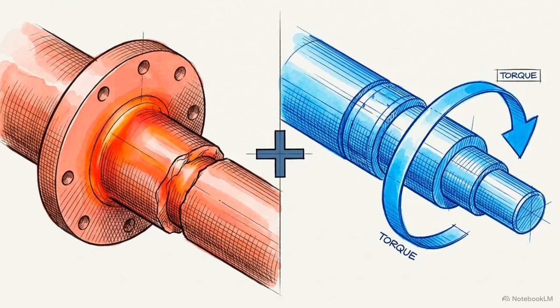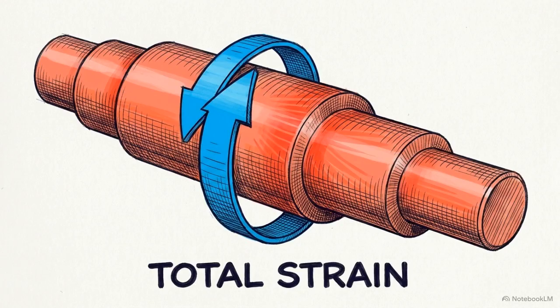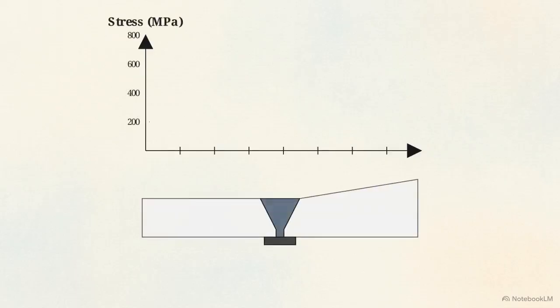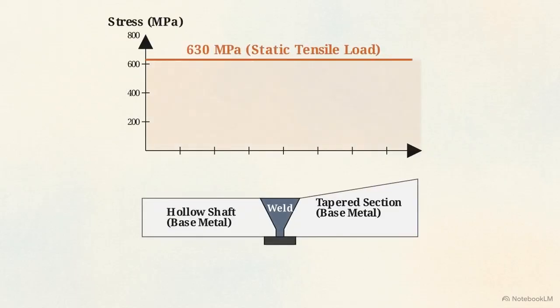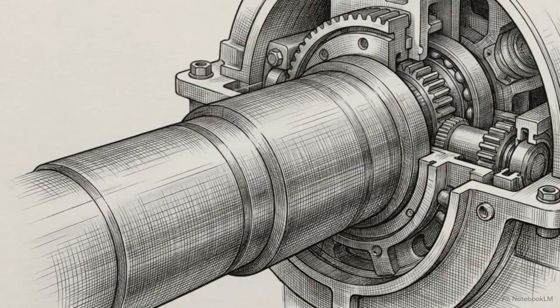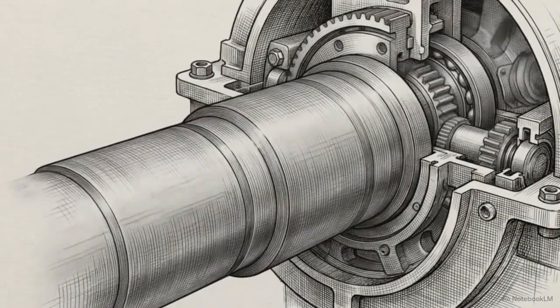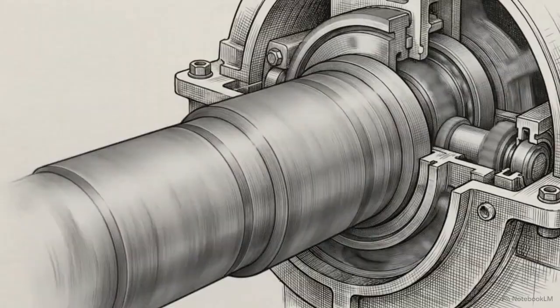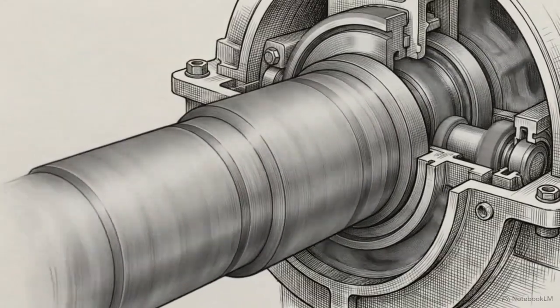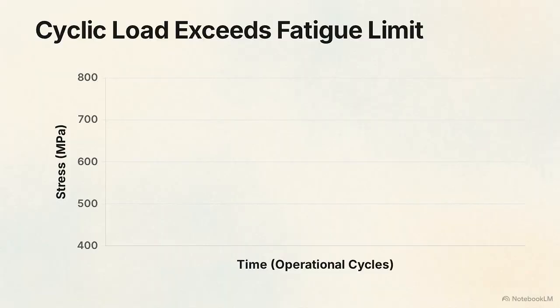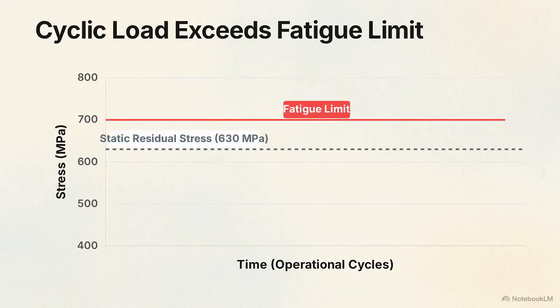To calculate the true strain on a component, engineers use the principle of superposition, adding static residual stresses and cyclic operational loads together. This graph plots the baseline stress. The static tensile load of 630 megapascals sits inside the base metal at the point where the weld was terminated. Once the massive hydro generator is activated, it introduces a continuous cyclic operational torque at 225 revolutions per minute. When this cyclic operational load is superimposed on top of the static residual stress, the total stress level rises.